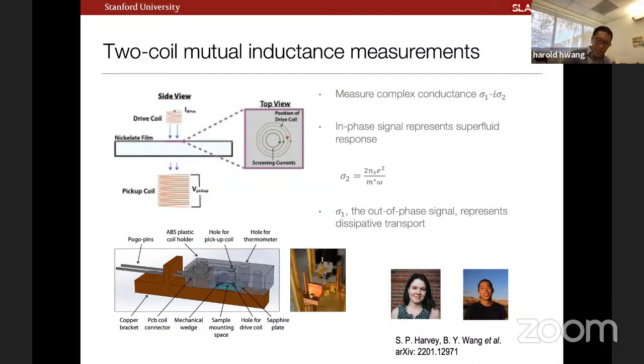And so our TCs are a little bit on the low side. And so in order to go to the low temperature regime, to make our best statements, as far as we can, about the possible implications for symmetry, or at least whether or not there are nodes, we're doing these measurements down to dilution refrigerator temperatures in this kind of a system.